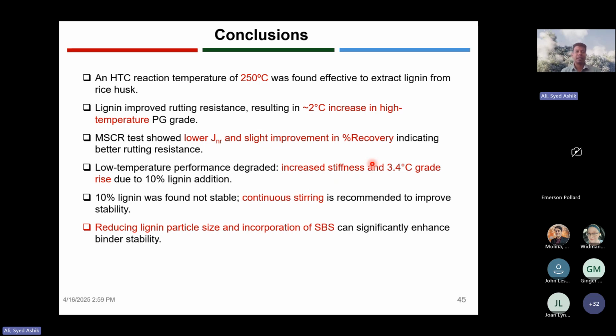If we use 10%, but if we use 5%, we may not see that much increase. We may see around 1 degree to 1.5 degree increase in our performance grade with 5% lignin. Multiple stress creep recovery test and also other tests have shown that the rutting resistance with lignin modification will be improved significantly. Low temperature cracking resistance could be a problem, but we have seen with 5% it is still okay.